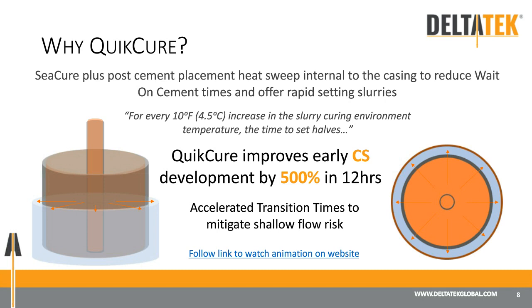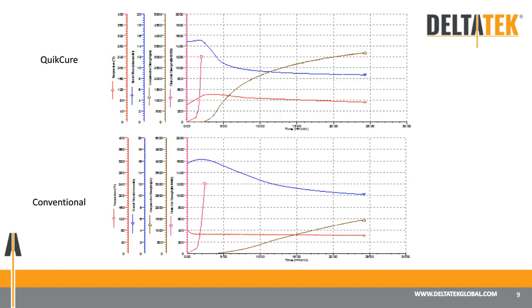Here is the exact same cement slurry. DeltaTek don't recommend changing the recipe of the cement slurry. All DeltaTek bring to this scenario is this heat sweep and the elevated slurry setting temperature. So here what we can see is the exact same cement slurry subject to the QuickCure heat sweep in the top of the slide and then set in the conventional lab test in the bottom of the slide. Now this is where you can see that the compressive strength, or the brown curve, is improved dramatically through the introduction of the heat sweep. The purple line, the transition time, is improved by circa 50%.